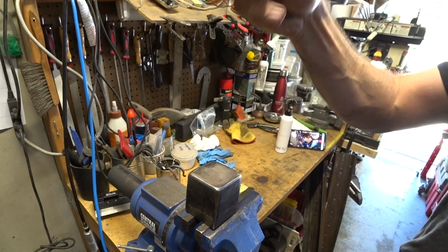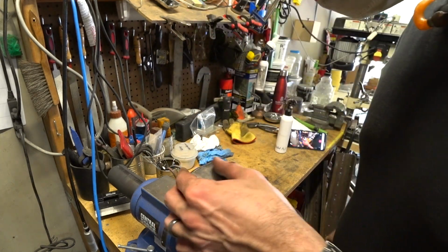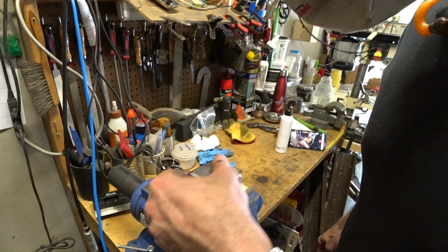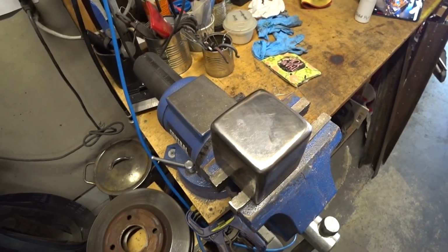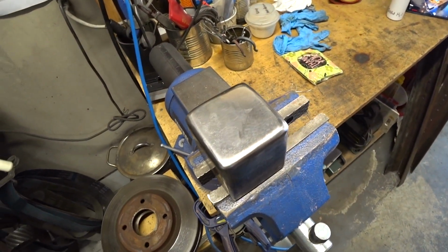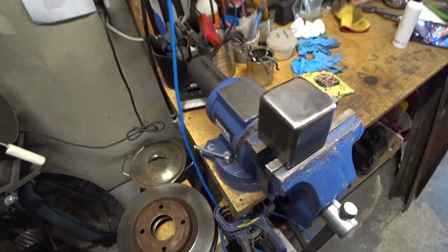But the main reason I was doing this test was to see if the ball bearing dented the surface. A soft steel surface would actually be dented by the ball bearing, whereas the case hardened surface was not marred at all. So now this anvil is ready for use.